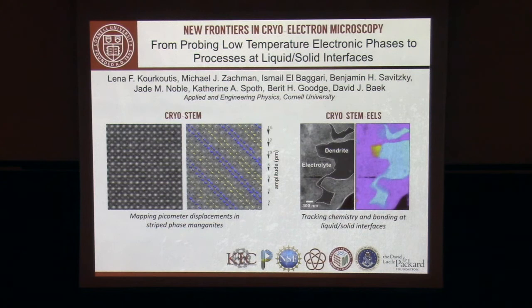And for that, I want to show you how cryo scanning transmission electron microscopy allows you to understand local distortion in the atomic lattice. So what you see, these stripes, is actually the stripe phase of a manganite. And what we are plotting is the displacement of an atom column in this stripe charge-ordered phase. And you see the distortions are on the order of picometers. So we need a technique that can measure at very high precision single atomic columns, that lets you extract those modulations at the relevant temperature where phases exist. And so that's what we have done with our cryo-STEM technique.